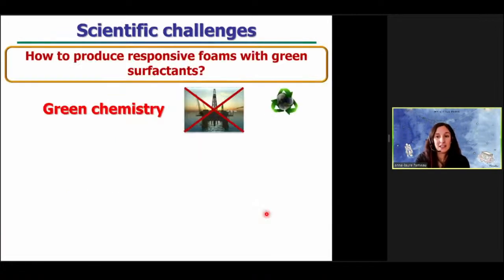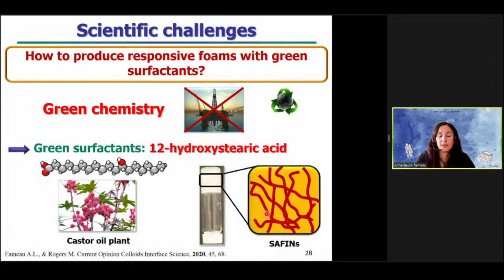But the scientific challenge is how to produce this kind of responsive foams based on green surfactants, to avoid the use of chemical defoaming agents. So our idea, our strategy, was to use as green surfactant a specific fatty acid. It's the 12-hydroxystearic acid. So it's a fatty acid with 18 carbons and a hydroxyl group on the 12th position. And these fatty acids come from the castor oil plant.